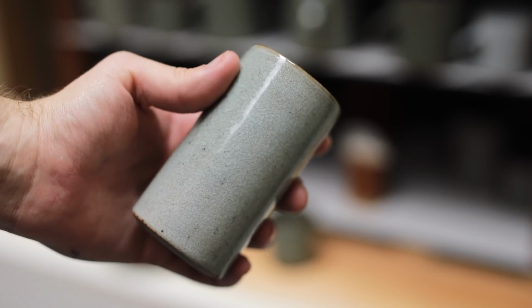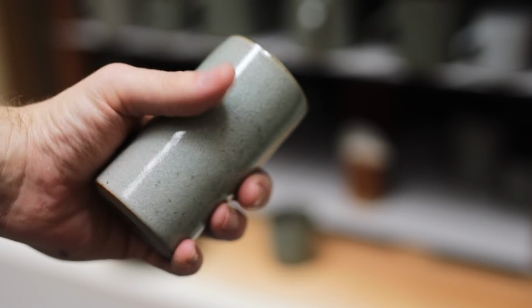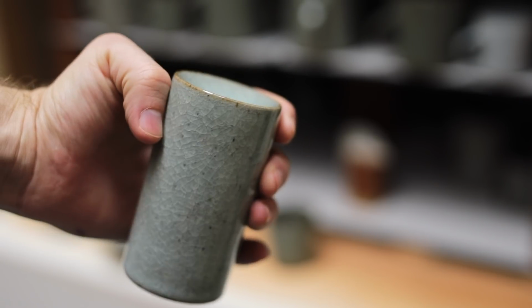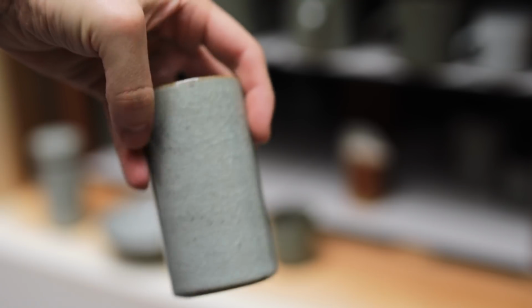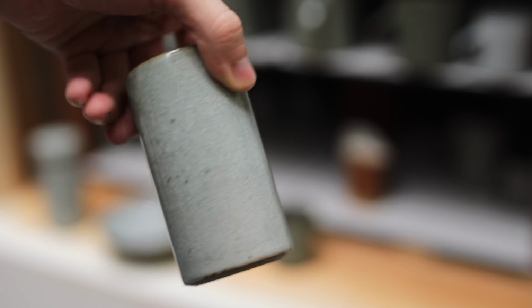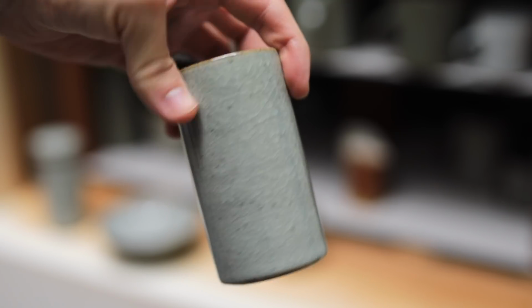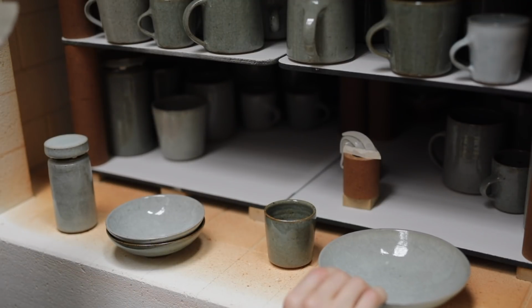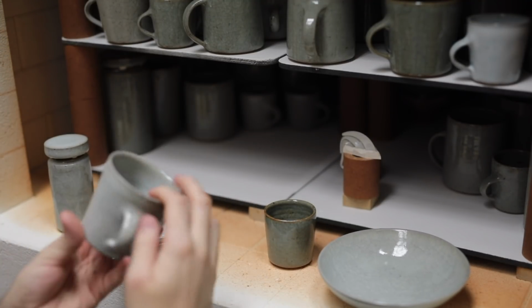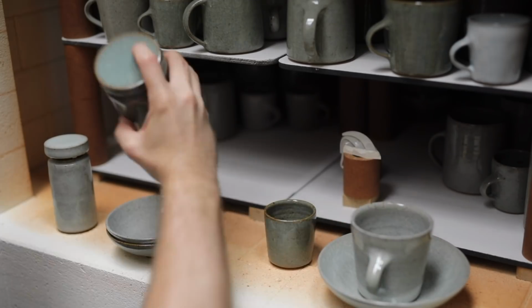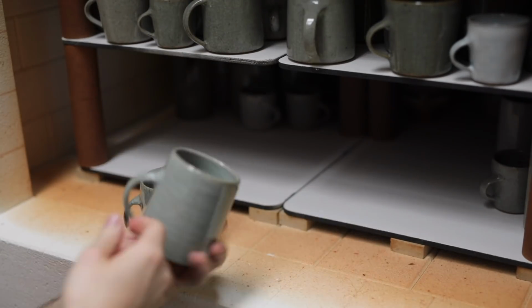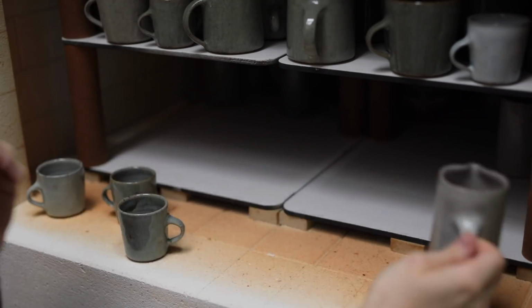So here's an underfired section, and as you can see it's quite matte, as compared to the opposite side of the piece, which is quite glassy. This piece makes the grade for a pot that I would refire a second time. Otherwise, these kilns are quick to unpack. I generally start at the bottom and work my way upwards, although there's no real reason for any of this.